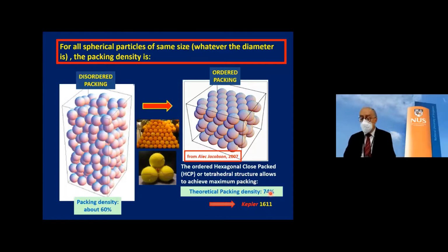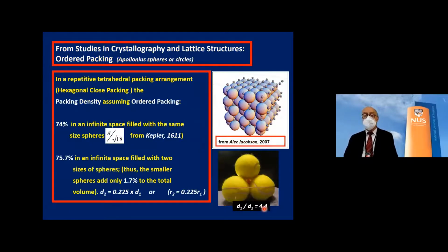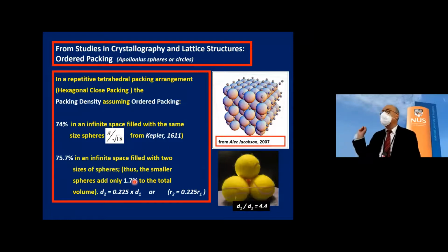And this particular result was already obtained by a mathematician named Kepler, in 1611. In fact, he gave the formula. The packing density of an ordered structure, the way I showed it, is pi over square root of 18, and that's 74%. Not only that, he then calculated the diameter of these little spheres that you could fit in the interstitial space between the bigger spheres, calculated their volume, and he said if you put them all in these spaces, you get 1.7% more. So you go from 74% to 75.7%. That's not much.